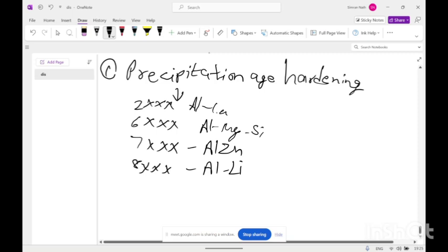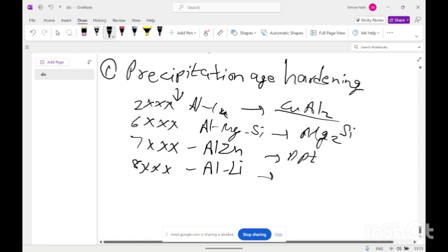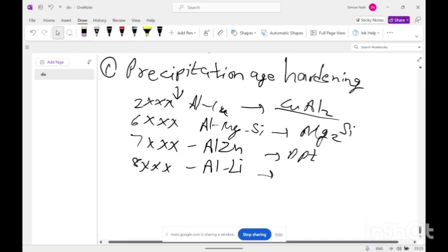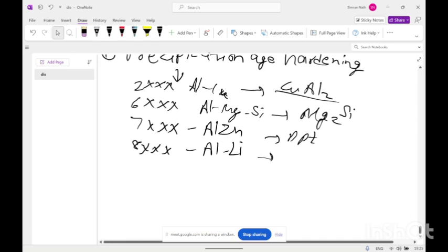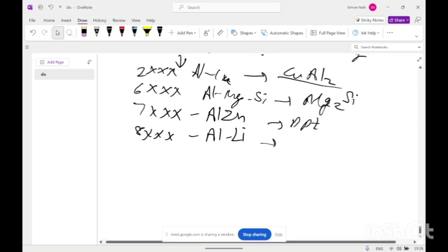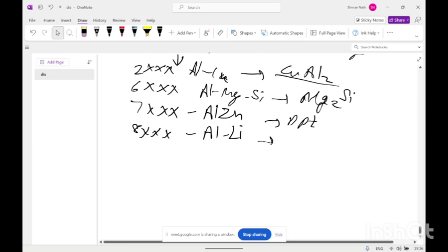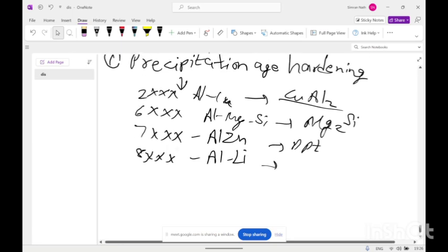The precipitation in aluminium-copper is the CuAl2 phase, an intermetallic phase. In the 6x series, it is Mg2Si, and there are also precipitates in the case of aluminium-zinc and aluminium-lithium alloys. The precipitation of intermetallic compound with aging leads to hardening and increase in the strength of the alloy. So how does precipitation age hardening happen?